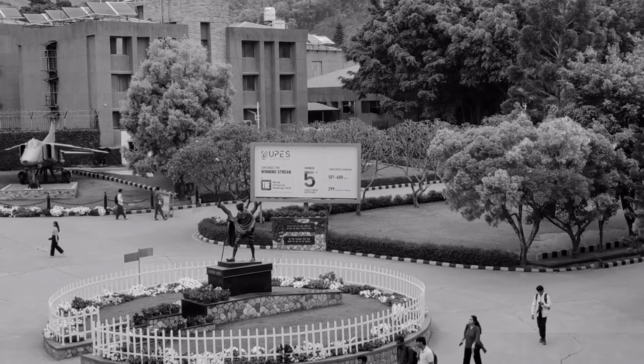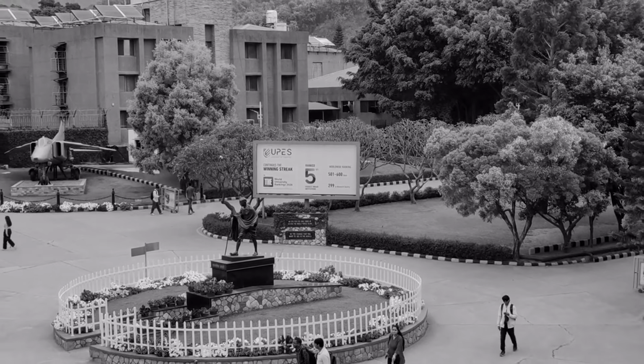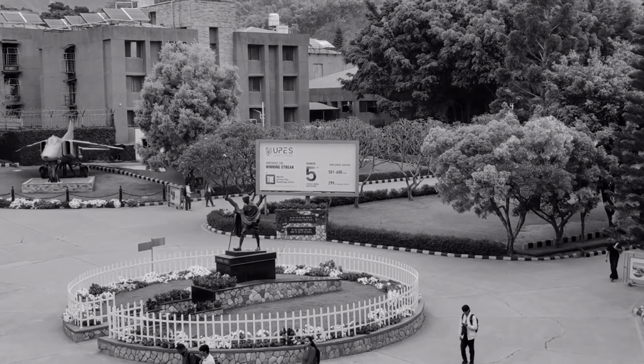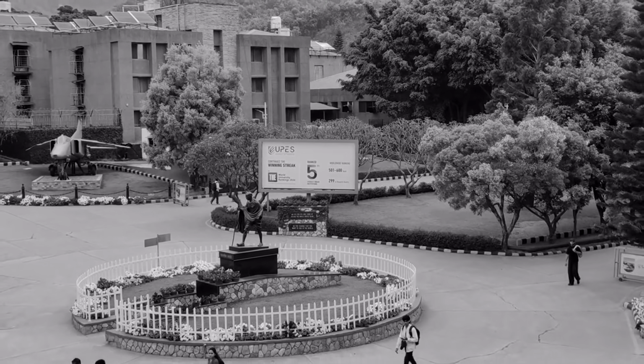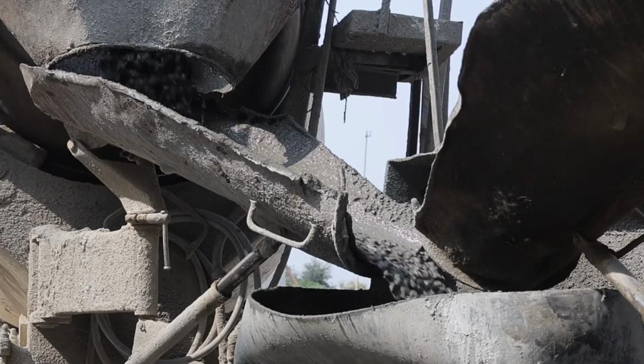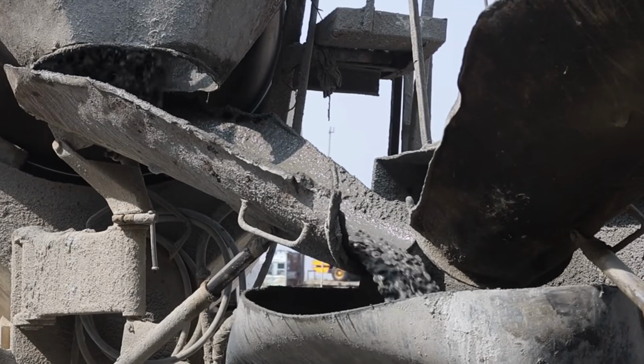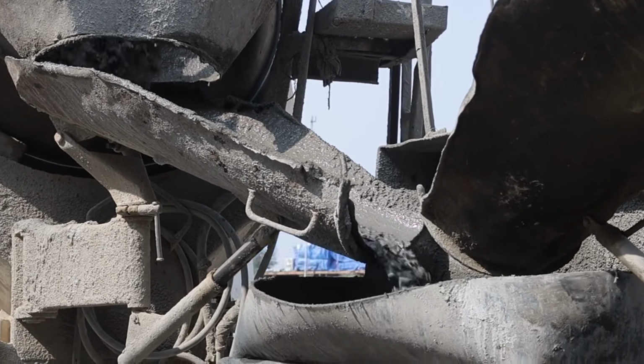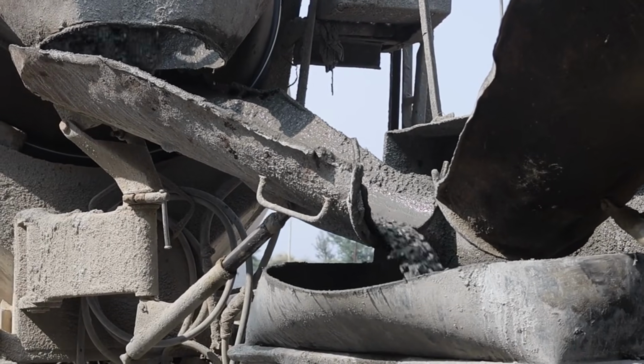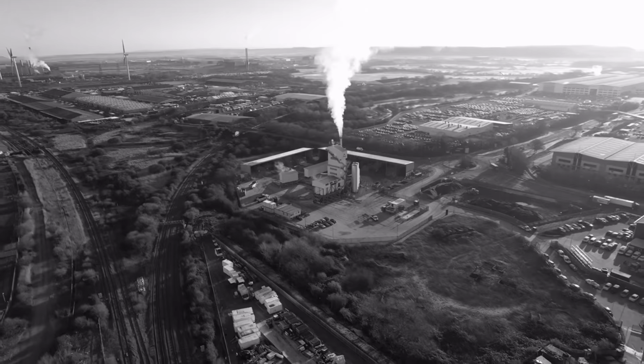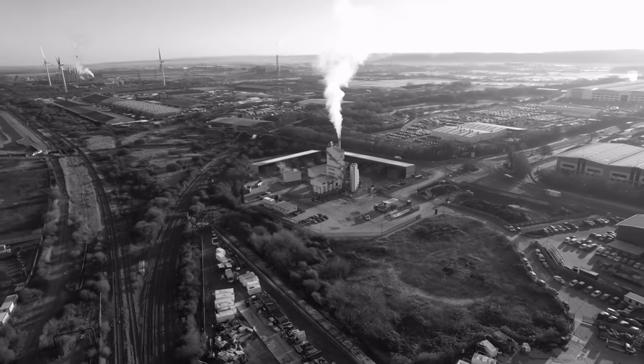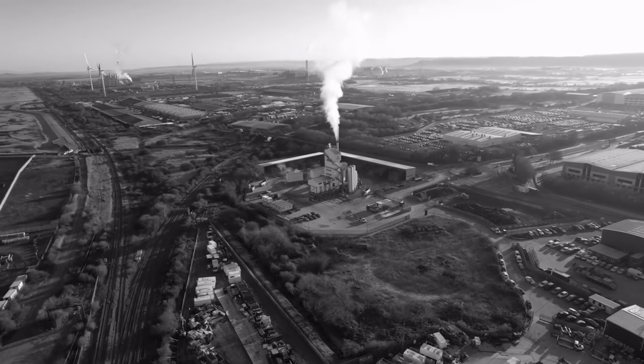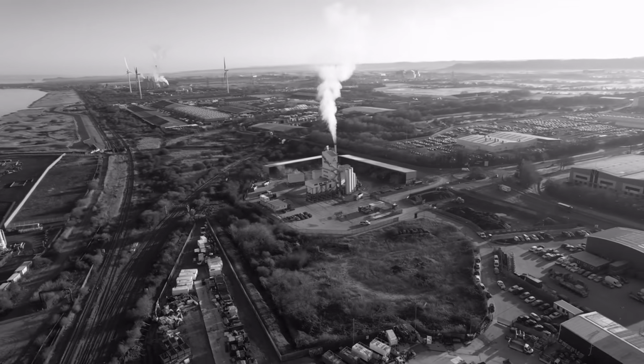The embodied carbon story is compelling too. Portland cement, the binding agent in concrete, is responsible for approximately 8% of global CO2 emissions. Every ton of cement clinker produced releases roughly 0.9 tons of CO2. A clay pot filler slab, by reducing concrete volume by 25 to 30% per structure, directly cuts the embodied carbon of the roof by a proportional amount.